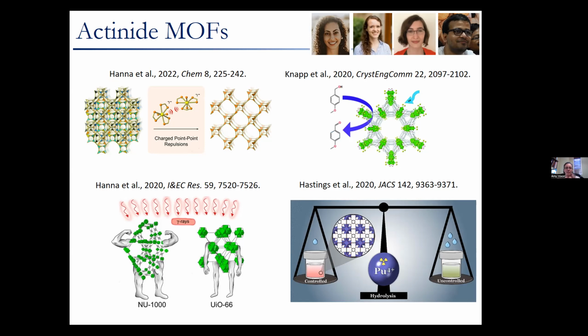But what she found was that if she left that interpenetrated MOF soaking in the mother liquor for a number of months, it slowly de-interpenetrated and became a single framework without any interconnections. So something that was very interesting, and like I said, really goes against thermodynamics and what we would expect at equilibrium. And so in collaboration with some of our computational colleagues, she was able to figure out that the reason this happens with this particular MOF is because of charged point-to-point repulsions. And so the MOF, when it is not interpenetrated, is really noteworthy because it's like 98% void space. So this means it might be a really good candidate for carbon capture or water cleanup or things of that nature. So it's an exciting avenue to pursue in the future.